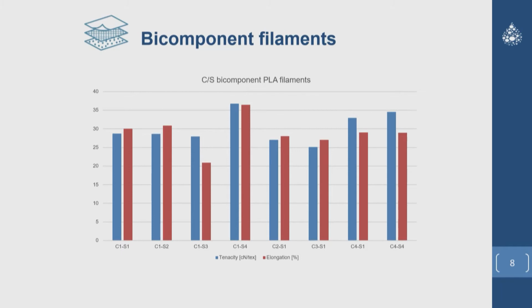composites. That's why the better results we have are made with a core that's a semicrystalline PLA grade, while the matrix is better to have an amorphous PLA grade. And so after improving and optimizing all the parameters and the PLA grades we used, we need to go to the next step, because with just some filaments, it's really difficult to go to a composite. At lab scale, we wind it around the frame, and it's quite easy, but in a production environment, you of course want to have something that's easier than manually winding something around the frame.